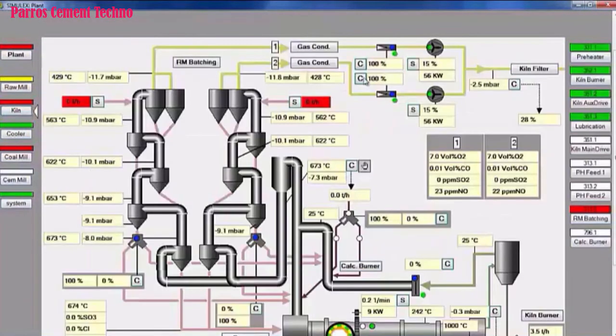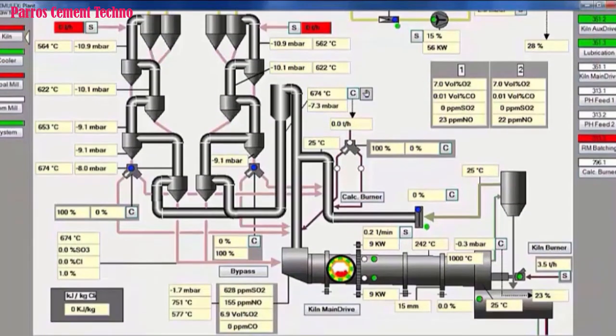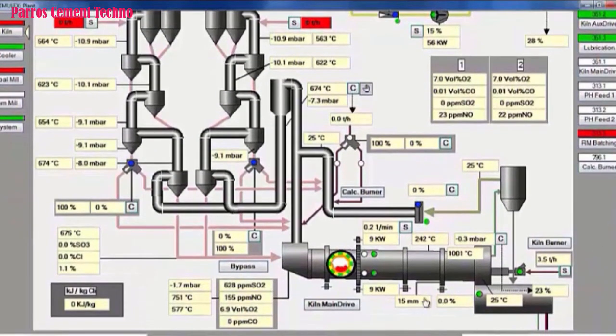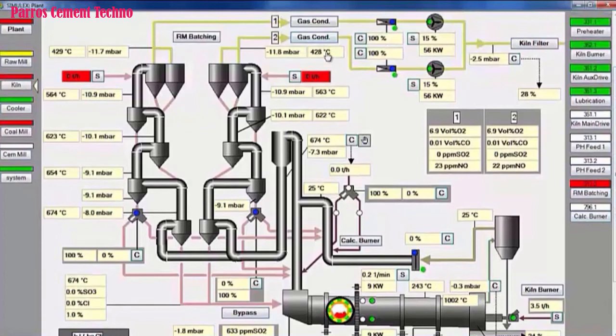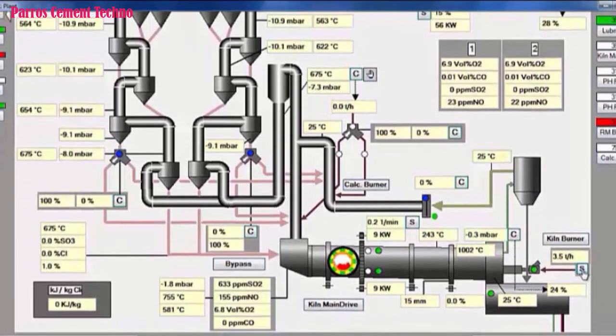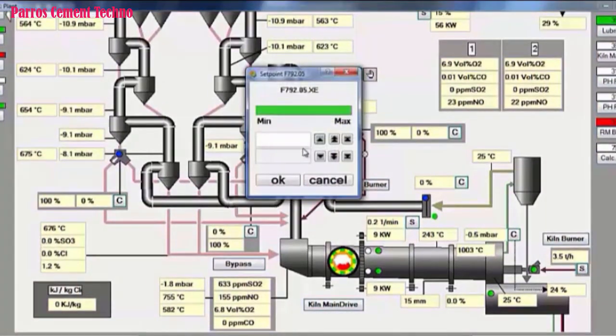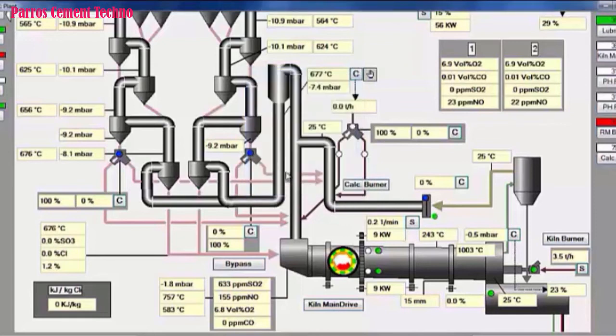Then we move the display to the main monitor. We observe all the parameters in the preheater and in the kiln. The temperature of the sintering zone is already 1000 degrees Celsius, and the temperature in the kiln inlet is 750 degrees Celsius, and the O2 is still above 6%. Because the preheater's top temperature is already high enough, so to add fuel to the main burner kiln, we don't increase the preheater ID fan speed anymore. But we can still add fuel, from 3.5 tons to 4 tons per hour.